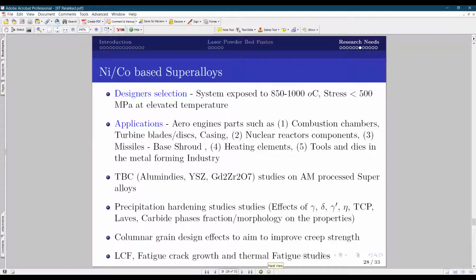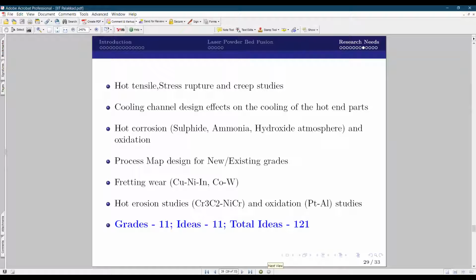Of course, low cycle fatigue, crack growth studies, and thermal fatigue are another area where we should importantly focus on superalloys. All high temperature properties like hot tensile, stress rupture, and creep studies data are very important in superalloys. And from the design perspective, how innovatively can I make the cooling channels to improve the efficiency of the cooling in the hot end parts. And hot corrosion studies, again like titanium alloys, oxidation studies, hot erosion studies, fretting. Because on one side titanium, on the other side superalloy in the aero engine. So all of them are more or less the same. And process map design for existing and the new grades. This is common for all the grades.